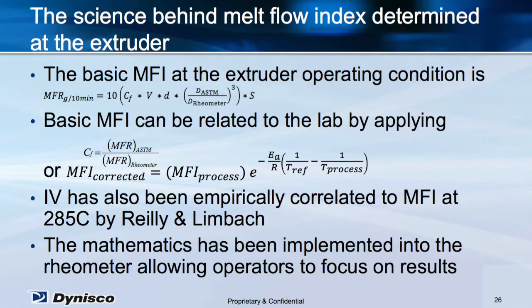So what we have done is talk about how to calibrate and set up an online rheometer to measure melt flow index. We've also discussed in detail how to correlate that reading to laboratory standard melt flow index using either a correlation coefficient or an Arrhenius relationship. We've also talked about how IV has been empirically correlated to MFI at 285 C.